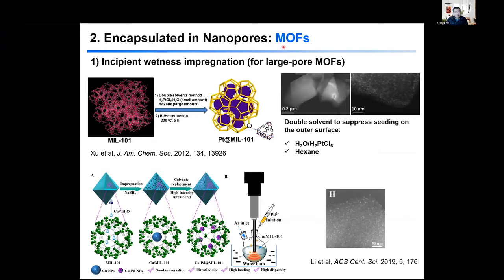Okay, and a new type of framework structure, MOF, and we can encapsulate nanoparticles into MOF as well. And then the typical method is also impregnation, and especially for large pore MOF structures. And the example shown here is the case people use so-called double solvent method. Basically the double solvent method is a mixture of small amount of water and large amount of hexane, and the water contains this platinum precursor, and so water can enter the pores of the MOF, but you don't have extra outside, so you don't have a bigger aggregation outside, and in this way you can produce really nice, very small nanoparticles within the framework.